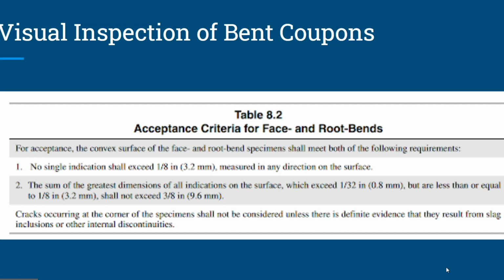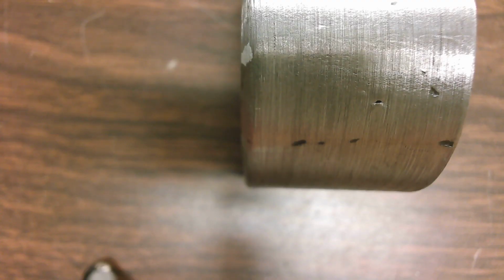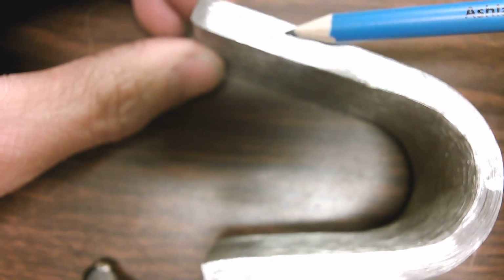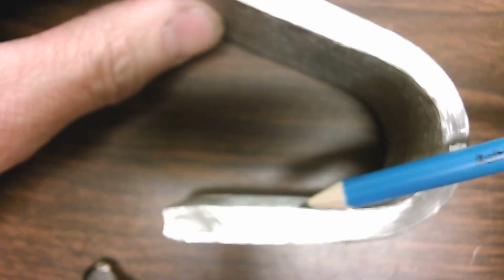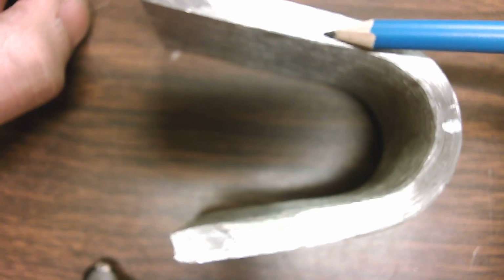So let's take a little video that shows inspection of a bend test. All right, so we're going to take a look at the face bend first. And so here's my weld coupon. This one had 2 pieces that were a little bit different in size. This one was probably closer to 3.5 when they were fitted up, and this one was closer to 3. That's why I purposely made sure I bent it on the center of the weld, but that's why this leg looks a little bit longer.